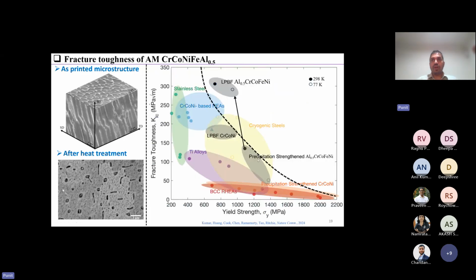And if we compare these fracture toughness values with respect to other known alloys, we see this material shows higher fracture resistance than cryogenic steel, and it also has higher strength than specifically designed cryogenic steels as well as stainless steel or these chromium cobalt nickel based high entropy alloys. And if we compare, you can directly see precipitate strengthening in these high entropy alloys and how it improves when you have this honeycomb microstructure.